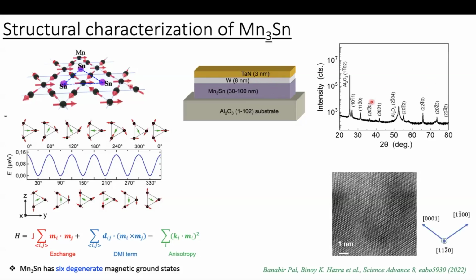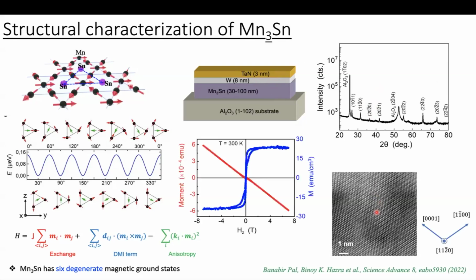Typically X-ray diffraction shows that the manganese-3 tin is oriented along the 112-bar-0 direction, so it is textured along this direction, it's not fully epitaxial. Further, the STM image shows the manganese-3 tin is locally highly ordered, and the Kagome plane can be seen clearly. Further, we performed the magnetization measurement. The red curve shows the raw data, and one can see the diamagnetic contribution of the substrate dominates in this raw data. When we correct the diamagnetic background, we observe this blue curve, so there is a small moment present along the Kagome plane.